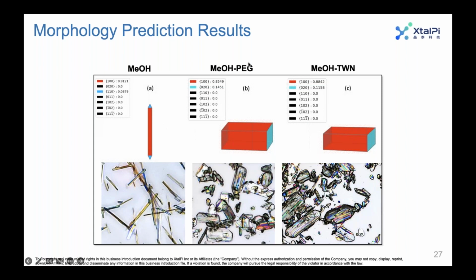Then we look at experiments that incorporate PEG or tween, and we see a dramatic change from the experimental results. We go from these extreme needles to much more block-like morphologies, and we're able to capture that qualitatively very well with the predictions. Something else I want to call your attention to that I'll talk about more towards the end of my talk.